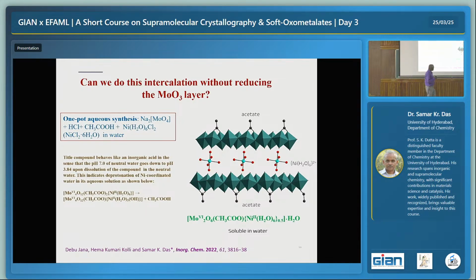So we have a single crystal structure, this is the compound, and to our surprise, all MoO3 compounds are water insoluble, but this compound is water soluble. This is a very surprising thing. What is the logical explanation? We believe, though we don't know the answer because we didn't do any computation so far, that because some electrolyte is there, the nickel aqua compound and acetate being a kind of electrolyte, that may make it possible to solubilize the whole system. It is an MoO3 compound, not molybdenum bronze so far, intercalating a nickel aqua compound, and it is water soluble.